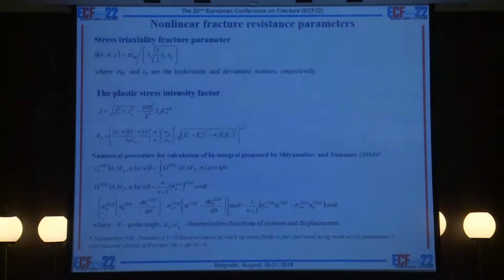In this study, we proposed to use the plastic stress intensity factor for mixed mode crack characterization. The plastic stress intensity factor can be expressed directly through the elastic stress intensity factor by using the well-known Rice J integral. And in order to calculate the plastic stress intensity factor, you need to know the values of the governing parameter of the elastic plastic stress field around the crack tip, the In factor. So in this study, we used a numerical procedure for calculation of the In integral proposed by our colleagues Professor Shlyannikov and Dr. Tumanov.